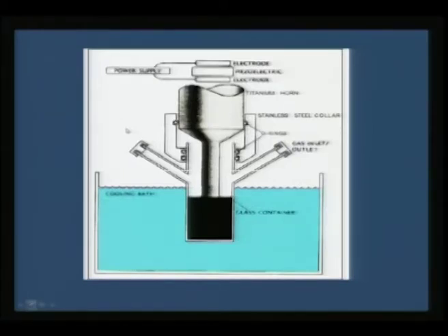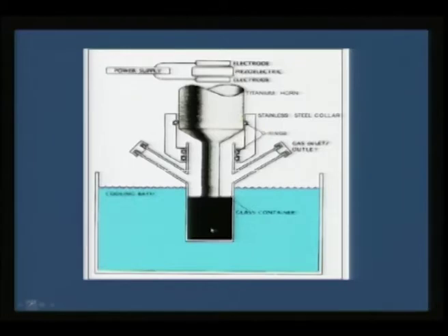Now once the sound waves come in, for a long time this will be trying to scissor the nitrosyl or carbonyl moiety from the metal, and after a particular time you would see the solution turning black. The moment the solution turns black, you can be sure that the metal nanoparticles are formed. So typically this conversion would take place of the order of say 1 to 3 hours, depending on the nature of starting material that you are employing. So once this is formed, then you can take the whole vessel into an argon glove box, and then you can carefully filter so that these metal nanoparticles can be preserved in inert conditions.